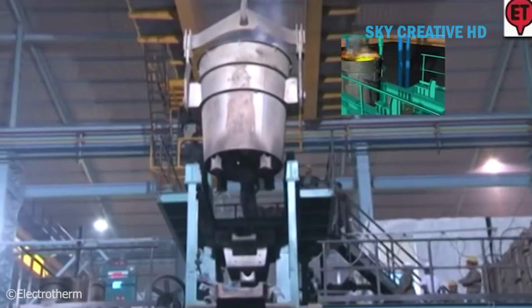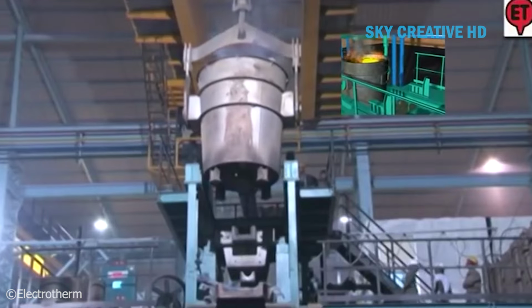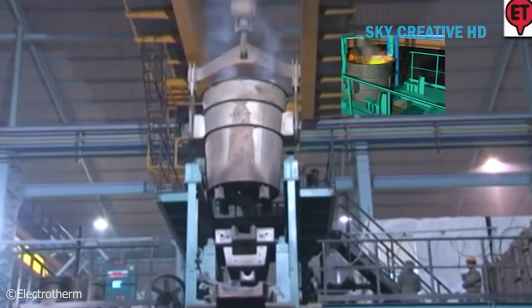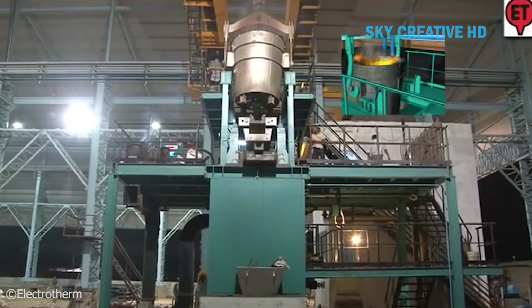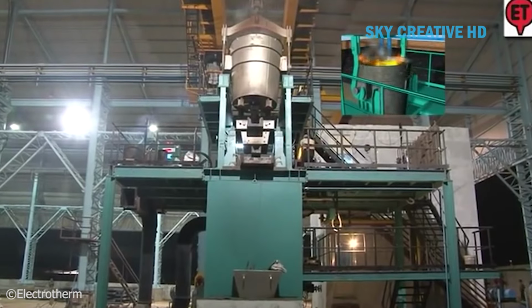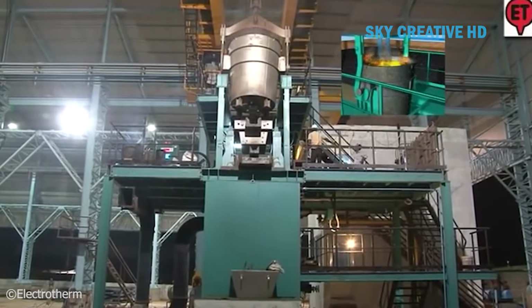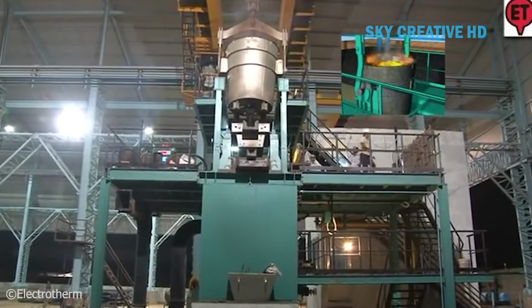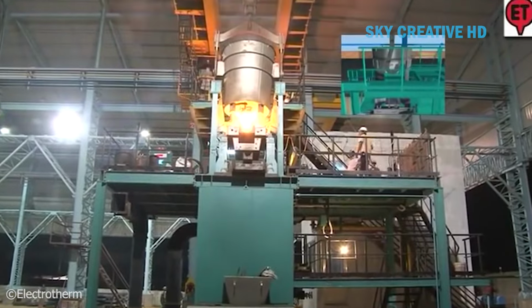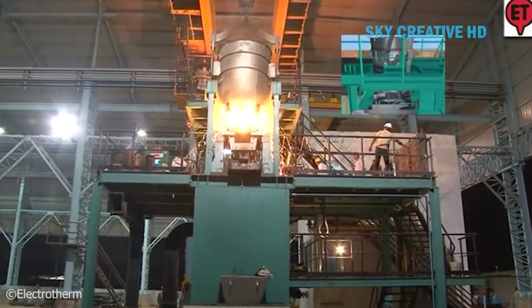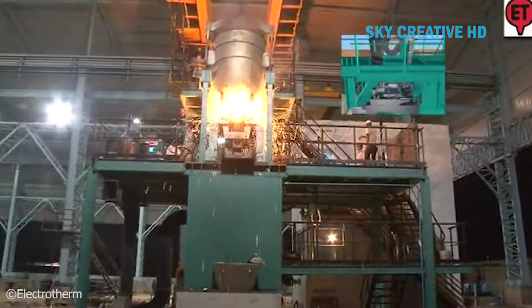solidification process. This isn't just random spraying. Sophisticated control systems adjust water flow to each zone based on casting speed, steel grade, and billet size. The cooling pattern must be carefully managed to prevent thermal shock that could cause cracks. Some zones use mist cooling, others use direct water jets, all coordinated to ensure uniform temperature gradients.